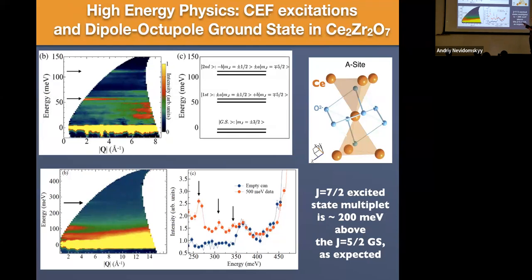At 10 Kelvin, you can forget about everything up here. The only thing that matters are these 2 states. And so this is what makes it a quantum problem, right? This is what gives you a small quantum number, because effectively, this is what we would call a pseudo spin a half degree of freedom associated with each cerium 3+ ion. And it's just these states here, and it's pseudo spin a half because there are 2 of them. I'm going to come back to that in a second, though.